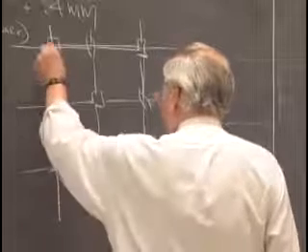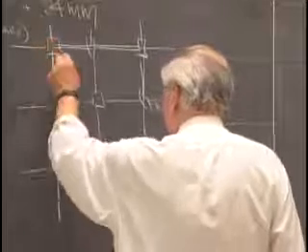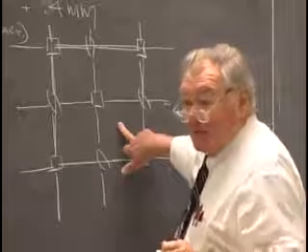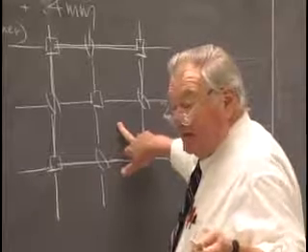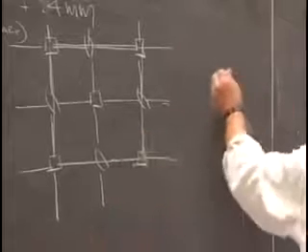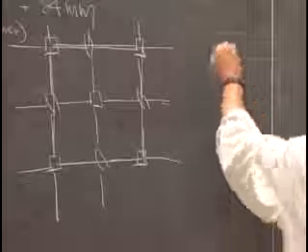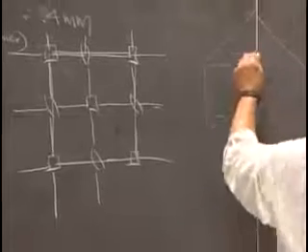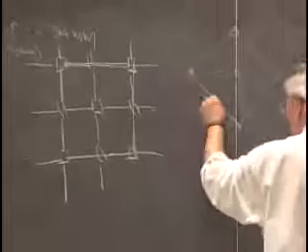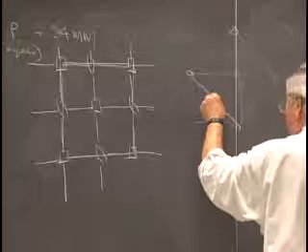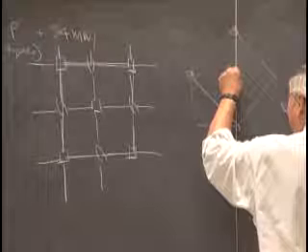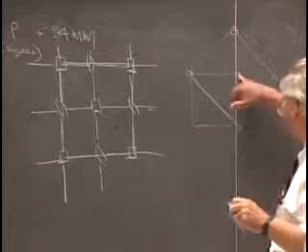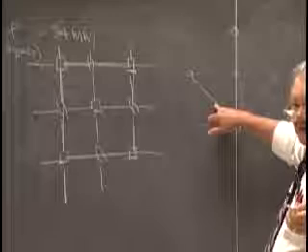And now we have a different kind of mirror plane, and we try to put it in this location. This mirror plane says, hey, I have to be parallel to the edge of a rectangular net or a centered rectangular net. So if we look at the translations that are parallel to and perpendicular to this translation, lo and behold, this mirror plane is aligned along the edge of a centered rectangular net that has the additional specialization of being a square, centered square. But that mirror plane now is perfectly happy, and he says, okay, I'll hold my peace.